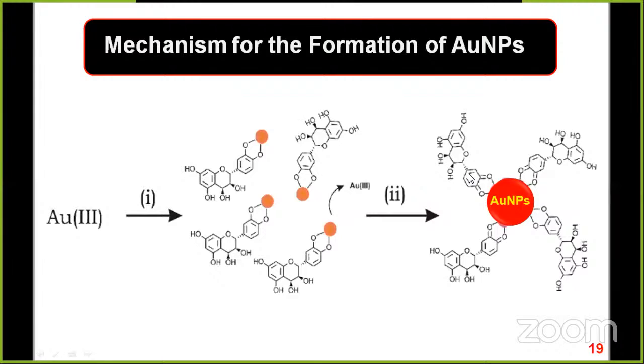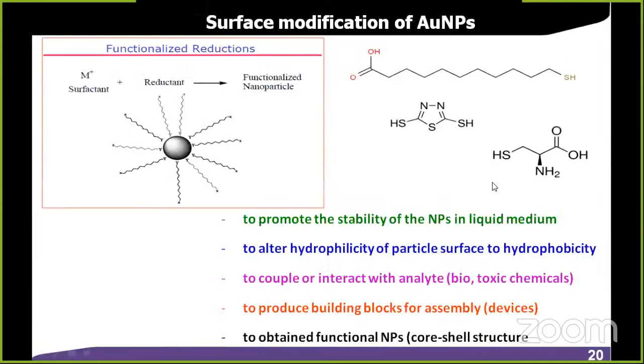Sometimes you can keep OH, catechol OH also. So these functionalities should be there at both ends. Both ends SH is okay, both ends COOH is okay, but it should be SH or NH2 or COOH. So one end can bind on the surface, and the other end is free from the binding, so electrostatic repulsions will come. These promote the stability of the nanoparticles, alter the hydrophilicity, and also allow coupling with biomolecules, and we can also make building blocks and core-shell structures.